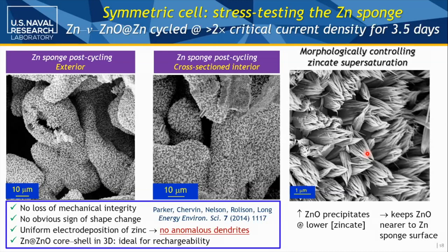And this taught us two things. You've got a confined volume in the pores, so you're going to supersaturate the soluble zincate that forms when you take divalent zinc as you discharge and it sees hydroxide in the electrolyte. That will ultimately supersaturate and spit out water and make the zinc oxide. Now, if that zinc oxide doesn't go on the zinc, you'll never talk to it again. So this was telling us that now we've got a lot of uniformity in the system, a lot of neighbors, which on their own would definitely make a dendrite, but nobody wins out. They've all got to work well and play well together.